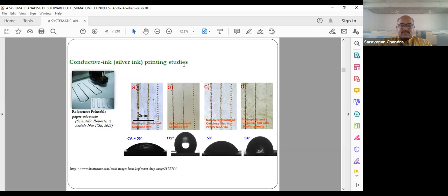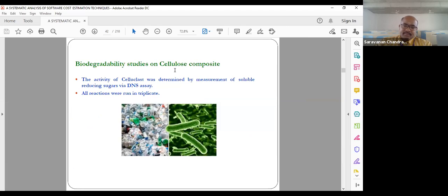So when you go for the printing studies, because if you make the material for electronic applications, the surface should be suitable for printing conductive ink coatings. The black one is the water droplet which is sitting on the surface. As you can see, when you increase the hydrophobicity, the place where it is conductive coated is a very finely defined structure which stays as it is, but in the first pictures it is spreading everywhere. It means it is absorbing the conductive ink, which is not suitable for printing. So with different types of coating, it becomes suitable for the printing studies.